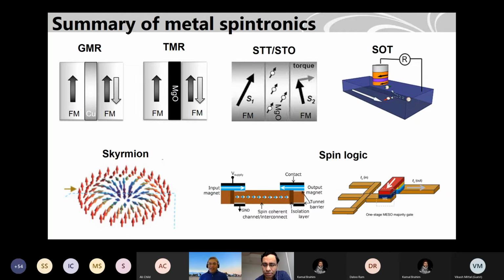So can we kill magnetic order by applying pressure and preserve topology? So I don't know whether you can kill the magnetic order, but you can tune the magnetic properties and the interactions for sure. I have not seen this, so I don't know actually, because if it is 3D materials, how sensitive they are to pressure. For example, maybe you need very high pressure in gigapascals to do that, but it may not kill magnetic order. But in the correlated material systems, for example, like oxide interfaces and twisted bilayer graphene systems, they are more sensitive because they are correlated phenomena and magnetism coming from the correlated electrons. So that may be more sensitive to this pressure and other parameters. Maybe somebody here can answer that better.